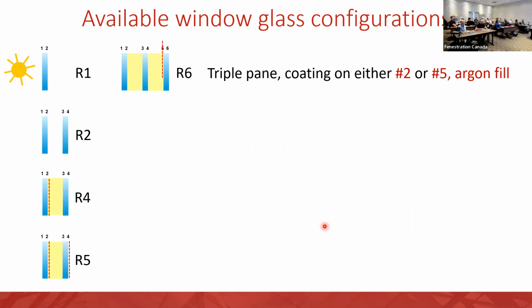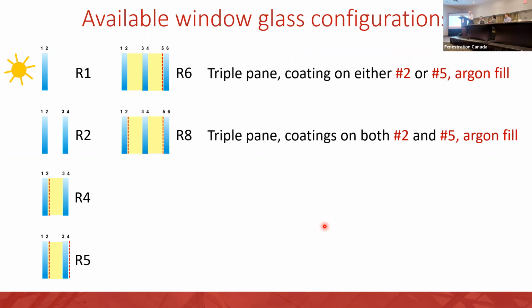Next option is to add another pane. And for now, we'll just stick with a single low-E coating. It could be on 2 or 5, but realistically, it's probably better on the 5 if you're trying to, well, it depends if your goal is maximizing solar heat gain or not. But this will bring you up to R6. So we've added an extra layer of glass, and we've gone from R5 to R6. Then we add a second low-E coating, and now we're up to R8. Triple pane, coatings on 2 and 5, argon fill. Any passive house window will work with this kind of glass. Any North American window will be fabulously comfortable with this kind of glass, even if it's not in a passive house frame.